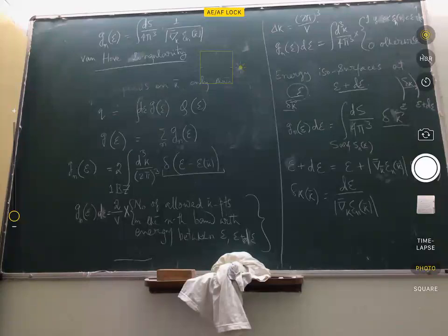Of course, you have a large density of states. Suppose you have a semiconductor, so some set of bands are completely filled and other sets of bands are completely empty. But then in the density of states in those bands, suppose you have such a singularity. So there are a large number of states available there. Density of states, remember, is the number of states in the energy range epsilon to epsilon plus d epsilon per unit volume. So apart from that volume part, it's the number of electronic states available in a certain energy range. So when there are a large number of states available, a large number of electrons can go there.